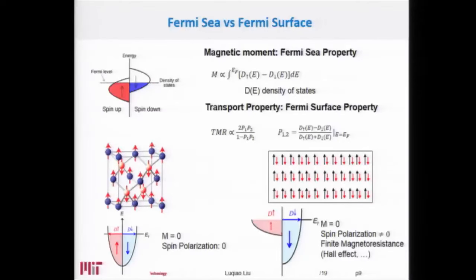If you compare this with the antiferromagnet case, as we said, for antiferromagnets there is a very high symmetry. So basically, spin up and spin down are completely the same, no matter which specific energy you talk about. At the Fermi level, you have the same number of spin up and spin down electrons, and at each of the other different energies, you also have the same number of spin up and spin down electrons. So that's the reason why in an antiferromagnet you have zero moment as well as zero spin polarization. But for a ferrimagnet, you can have zero moment, and at the same time, you can have finite spin polarization at the Fermi surface. And this finite spin polarization will allow us to read out the information easily from the material.